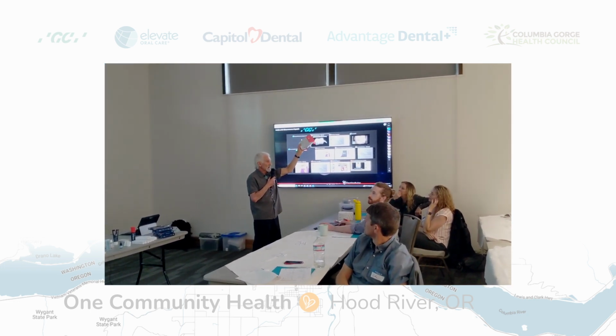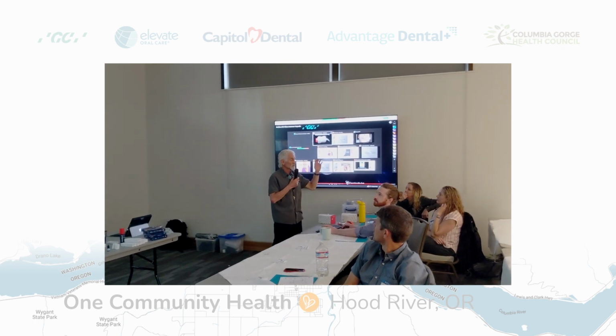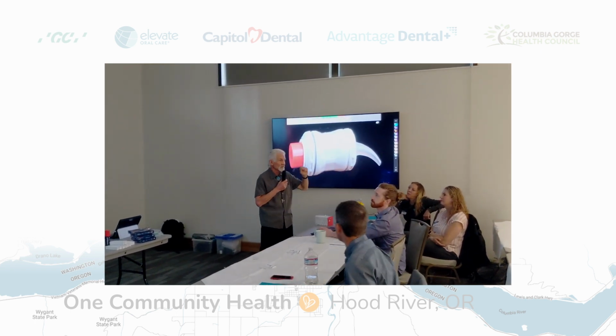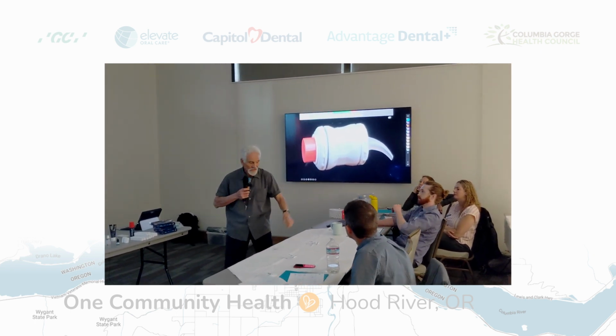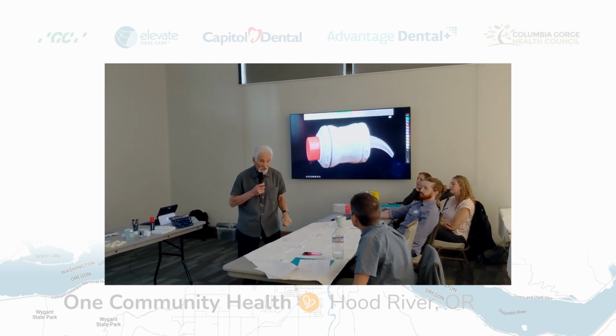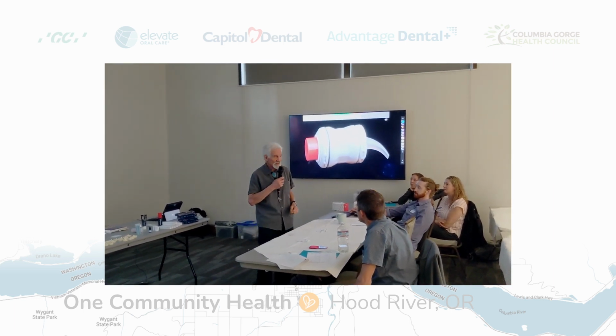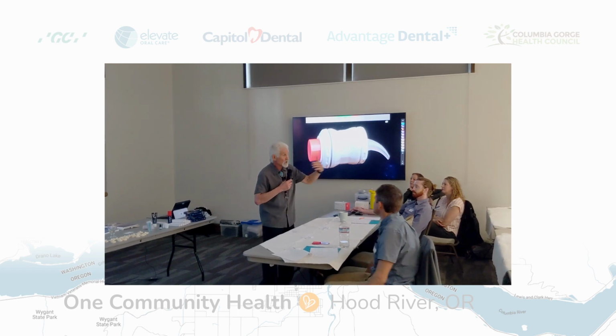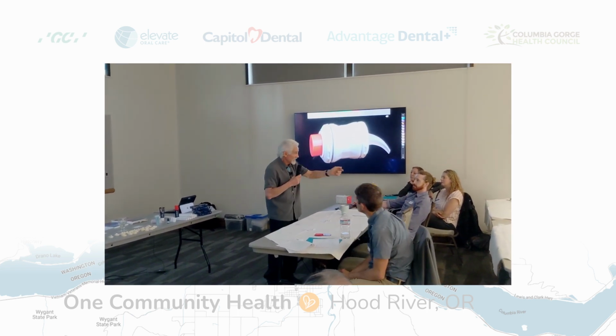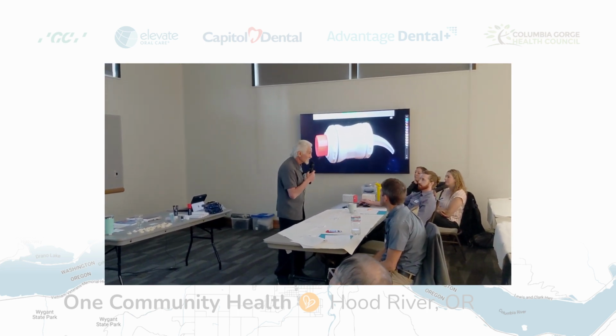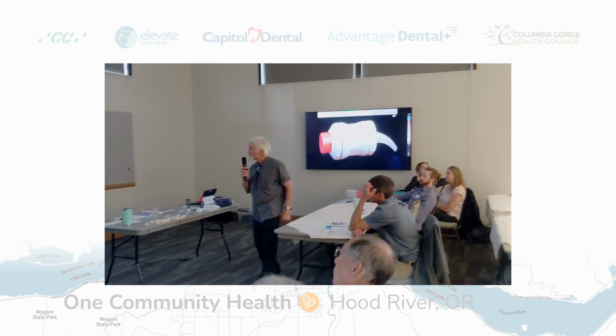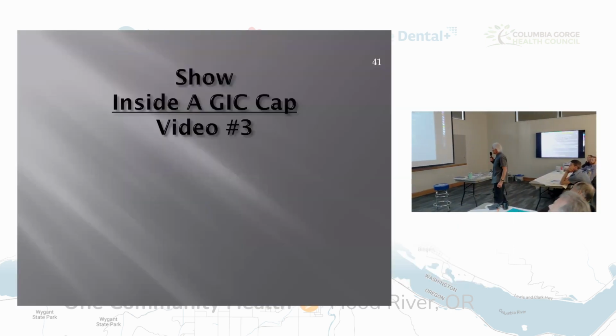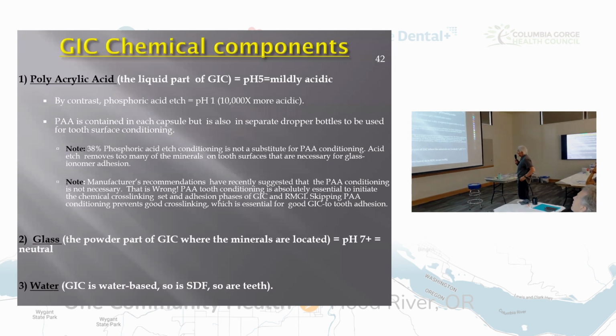You've got to fluff that glass up because what does it do? What does talcum powder do in your medicine cabinet? You know, it just kind of packs down. So you got to tap, tap, tap, tap, tap on a hard surface. Fluff that glass up and get it ready for the polyacrylic acid, the liquid. When it enters, it wants to enter a fluffed up glass so it all mixes well. Next, please. Okay. Polyacrylic acid.